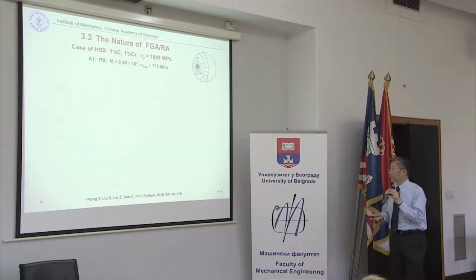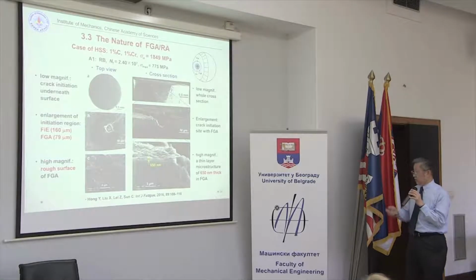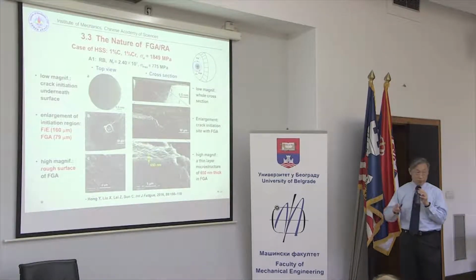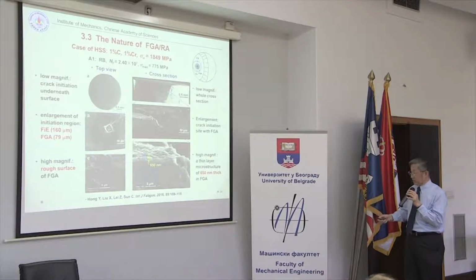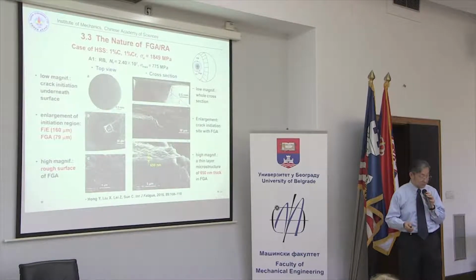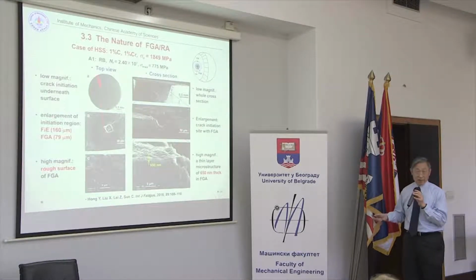So at this step, we would like to identify what is the nature of this initiation region. And for the case of high strength steel, we select an example to observe the fracture surface on the top, and to see again the fish eye and FGA and initiation spot from inclusion, and the FGA is a rough surface, and this cross-section morphology. And it's interesting that the layer of this rough surface is about 650 nanometers. But it's just a kind of rough observation.